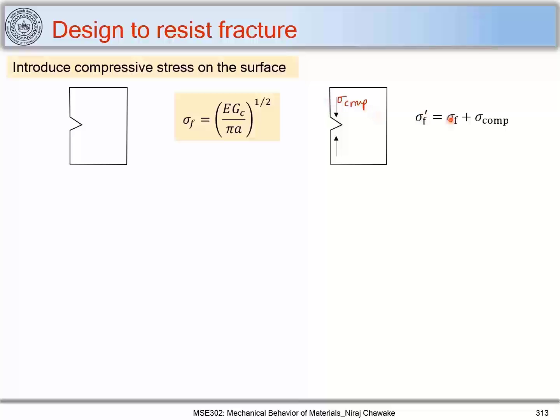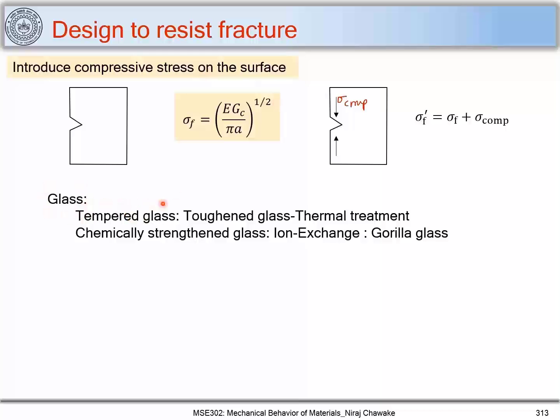So it is ideal that when you want to increase the fracture toughness of a material, always introduce compressive stresses on the surface. Now how is it done in glasses? You can check tempered glasses, which we use in our mobiles. This is also referred to as toughened glass, and we get compressive stresses on the surface by some thermal treatment. You can refer to any standard textbook for this. You have a glass and you heat it to some temperature, and you take this glass out and blow some air on the surface on both sides, and what happens is the surface layers get cooled faster compared to the interior of the glass, and that is why you create compressive stresses because of this differential thermal cooling.